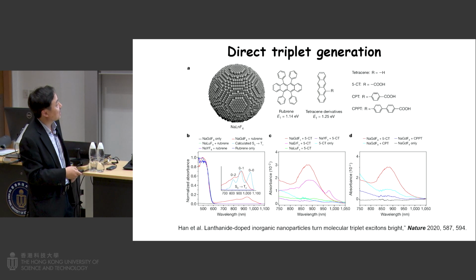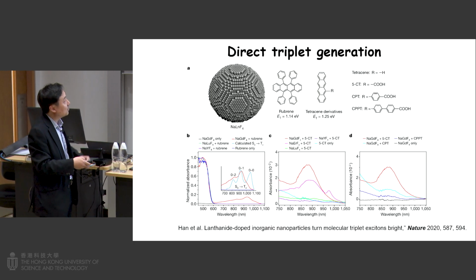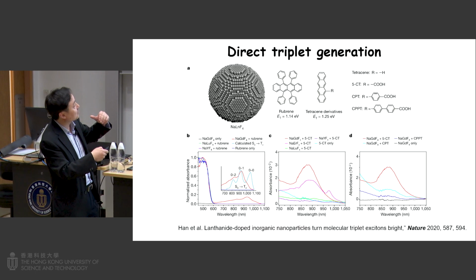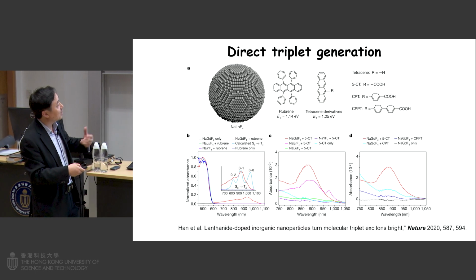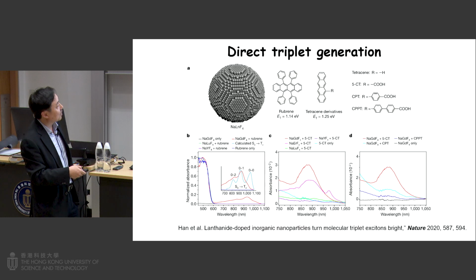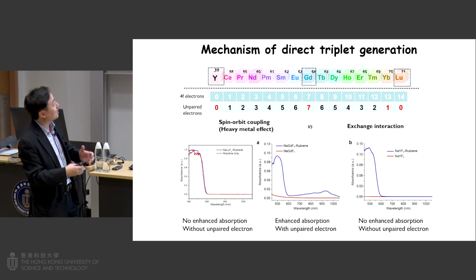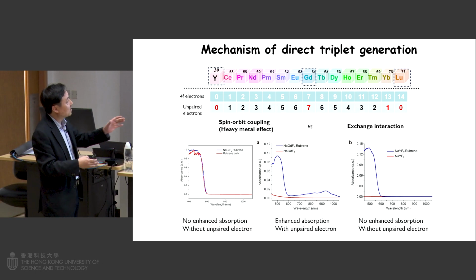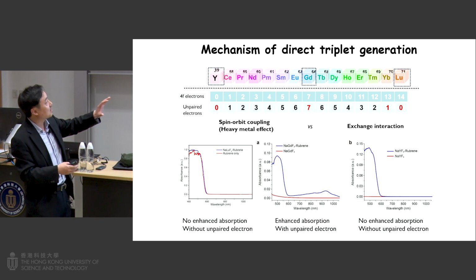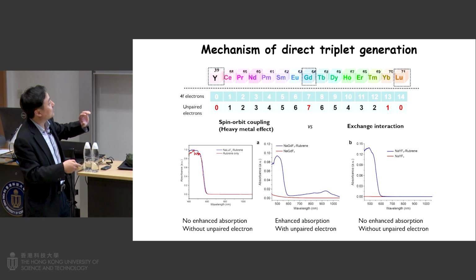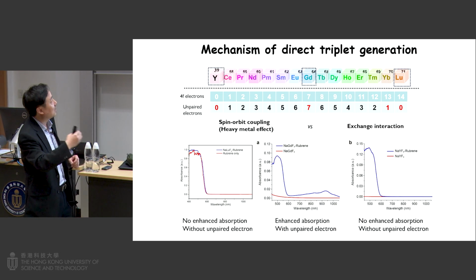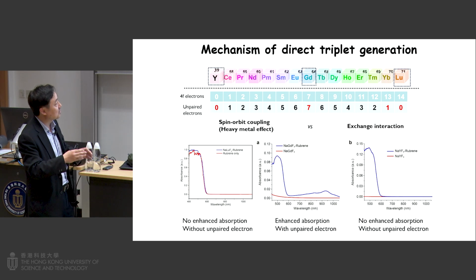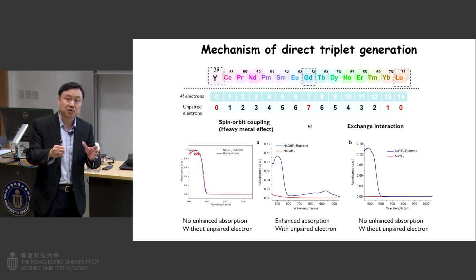For example, the tetracene and rubrene. With the lanthanide nanoparticles, we can actually enhance the triplet absorptions based on the data shown here. It's quite interesting. We can also enable direct triplet generation. So I want to highlight this interesting study. It turns out this direct triplet generation is associated with unpaired electrons.